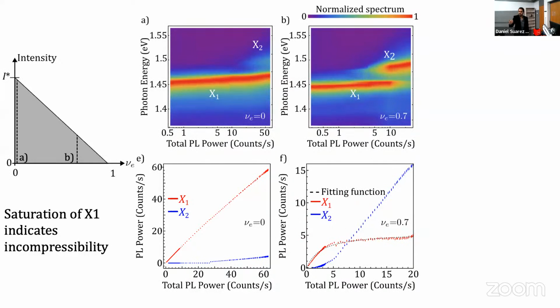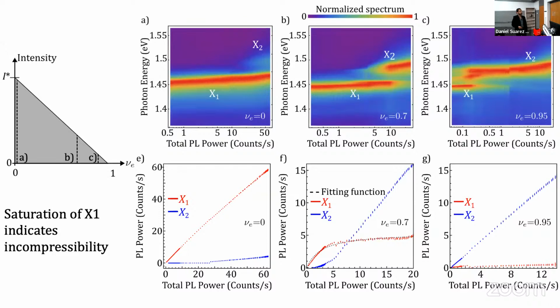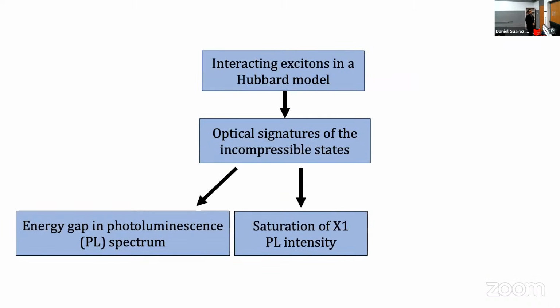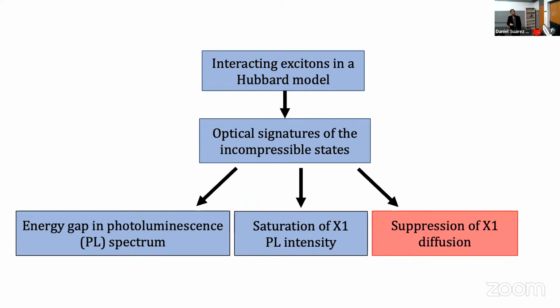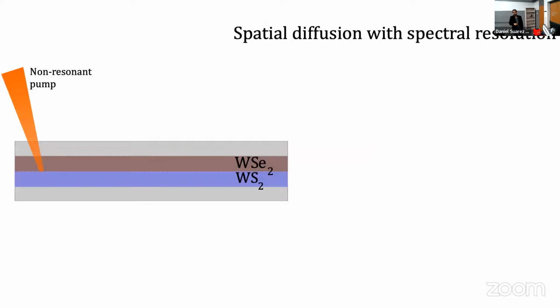So we are saturating the system with bosons, and then there is a threshold after which the whole system is effectively populated with bosons. And then the third evidence of formation of incompressible states comes from the diffusion of the excitons. The way we do this experiment is we pump our system non-resonantly with a very small, almost diffraction-limited beam. This will then create a population of excitons that, due to their nature, is going to propagate. And after some time, depending on their properties, they will recombine. And this recombination we measure with spatial resolution, so we can know what kind of exciton recombined from where.